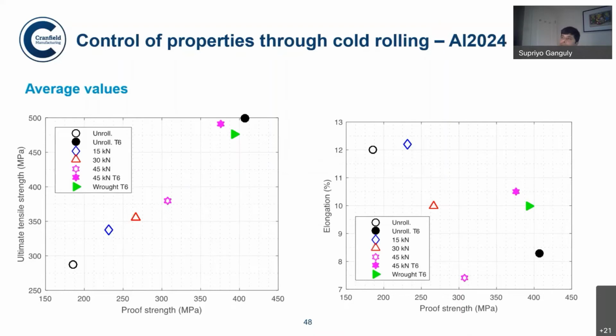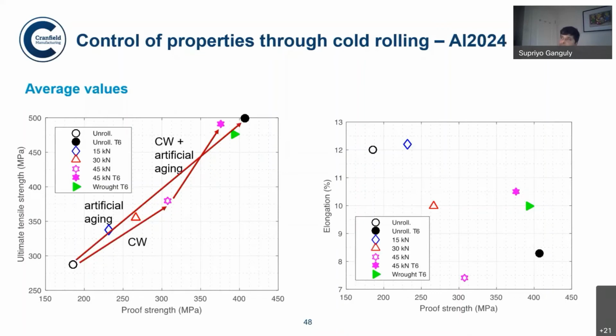And this is aluminum 2024. A very similar observation was also seen. So the 2000 series aluminum alloy can achieve its peak strength without any cold rolling. However, cold rolling can be extremely important to reduce porosities and other sorts of defects that normally accompany aluminum deposits. Also, a cold rolled structure generates much better ductility or toughness as compared to a directly aged alloy. So in those respects, cold rolling can be a very important aspect that should be followed in aluminum alloys as well.